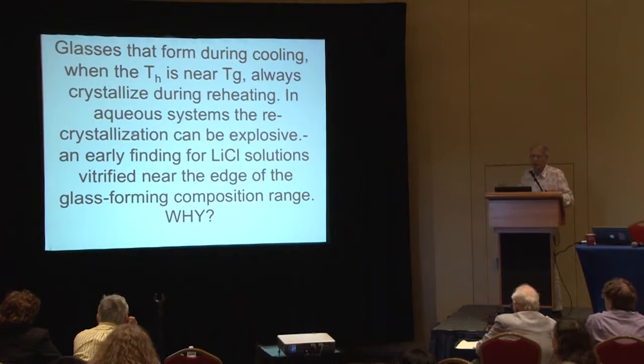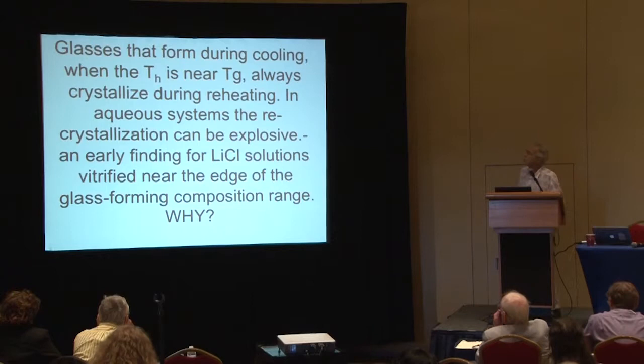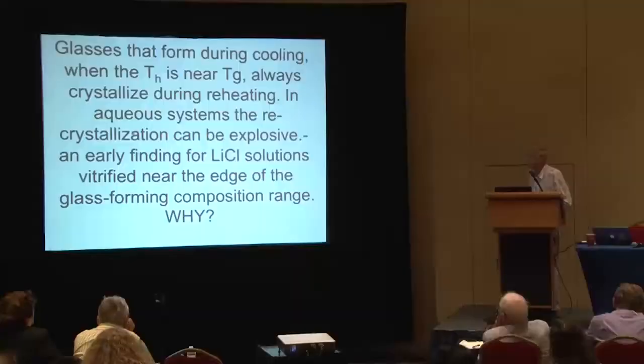And that recognition is important to understand this observation here, where we see that the systems which are vitrified during cooling, when the TH is quite close to TG, always, simply always crystallize during reheating. And it's a bugbear in general that you don't have this symmetry. If you want to avoid crystallization at any point, you have to reheat much faster than you cooled. And I want to explain how that just falls out of the next part of the experiments,